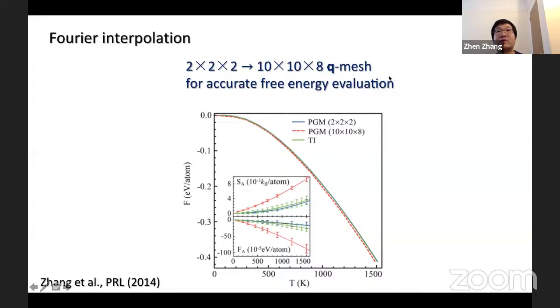From the Fourier interpolation, we further evaluated the entropy and free energy with a dense converged 10x10x8 Q mesh. And there is a noticeable deviation from results obtained with the 2x2x2 Q mesh. Such difference can impact significantly on the phase boundary and thermodynamic calculations. However, conducting TI from ab initio MD with a large 10x10x8 supercell is beyond the computational capacity. The present method can overcome such difficulty in accurate free energy calculations.